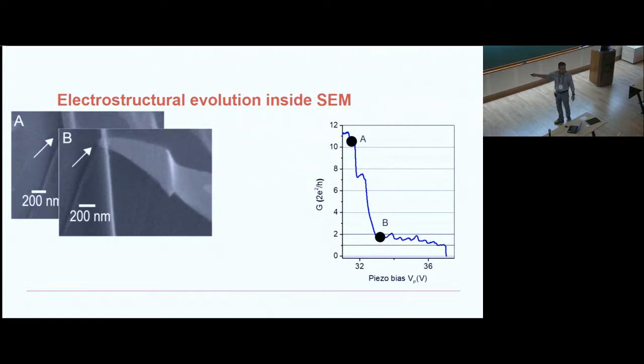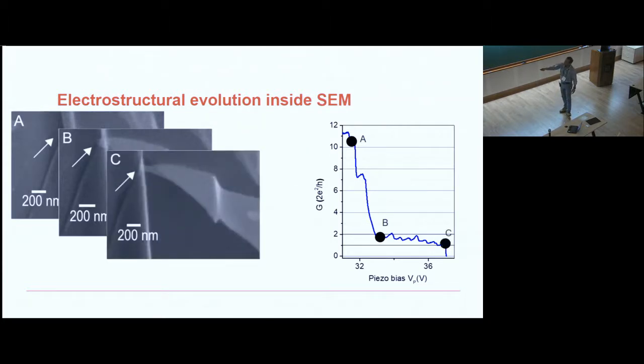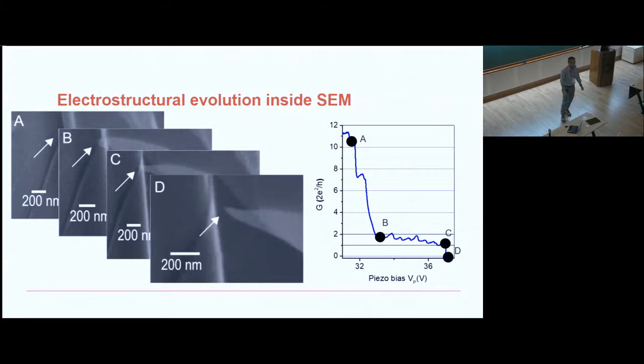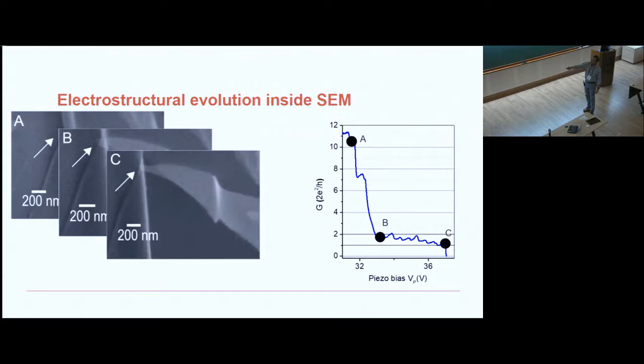The conductance dropped significantly. I go farther up. I have now moved to a bridge of less than 10 nanometers. This is why it's called a quantum point contact. The bridge is extremely narrow over here, and then when I pull the bridge out completely, the conductance drops. What is interesting here, you can see that when I'm in this position with the bridge less than 10 nanometers, my conductance is actually tending towards the universal conductance of 2e²/h, okay? Not something which is arbitrary. And that's the key result of the work.